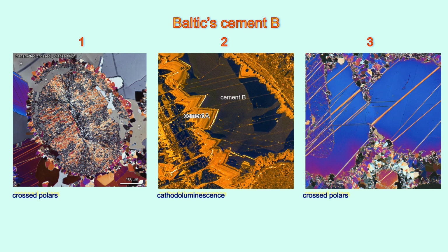After cement A had precipitated, the larger cortex cavities in section 1's ooids were fractured, before cement B precipitated and healed these fractures. Cement B's randomly oriented crystals were initiated tens of microns apart on cement A's final euhedral surface. The lack of connection between the two cements was probably due to a pause in precipitation when cement A's surface aged.